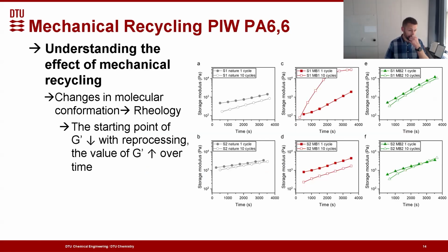And if we then look at the rheology plots as storage modulus versus time, we can see that for all of the samples, we see an increase in storage modulus as time goes on. That indicates that there's a reaction going on, the system changes. On the other hand, what we can also see is that after multiple recycling steps, the initial modulus is lower, which means that we have had some chain cleavage taking place in the samples. What we can also see is that once we measure on samples, particularly 10 times recycled samples, for some of them we actually get a severe cross-linking taking place inside the rheometer.